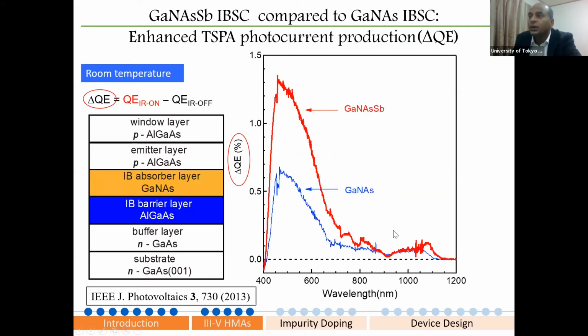And here, using dilute nitride semiconductor material in a solar cell, we have N-type material, we have P-type material. So this is a PN junction, and in between the PN junction, we have intermediate bandgap solar material. And here you see, if we don't have this intermediate bandgap material, you will not see any two-step photon current. It should be a straight line, which is this dotted line. But if you have an intermediate band solar cell, I show you here that due to that intermediate band state, we have a lot of photon current we can generate.